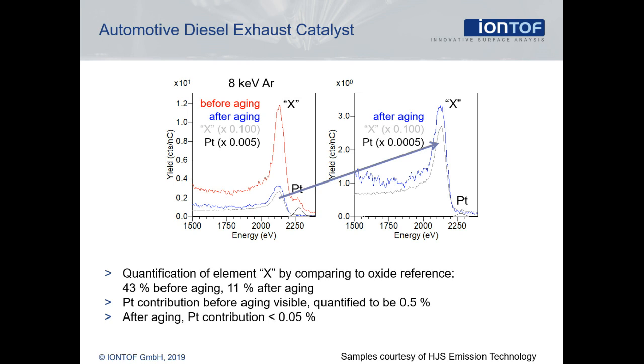Platinum is the active phase in this catalyst and the X oxide is the support which acts as an oxygen source/sink for the oxidation reaction. This means the aging inactivates the catalyst by removing platinum from the surface, either by evaporation or integration into the bulk.